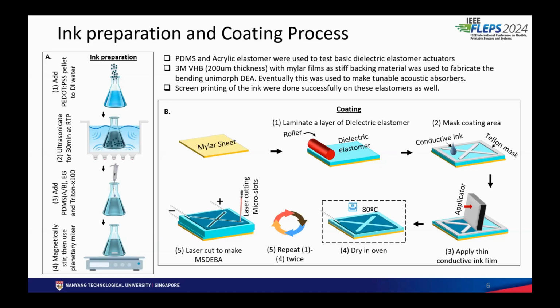When coated, it can easily be coated on any of the low surface energy substrates, and this is how we make the bending dielectric elastomer actuator. This is a Mylar sheet. We laminate it, and then we coat the ink. After coating the ink, we cure it, and eventually, to give it a different kind of shape to open up, we do laser cutting.